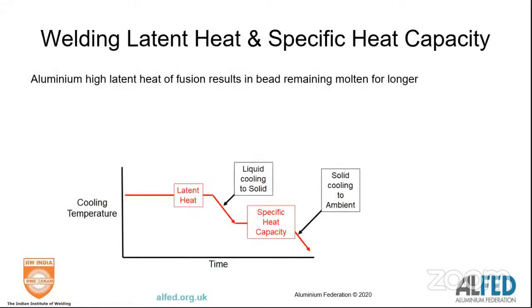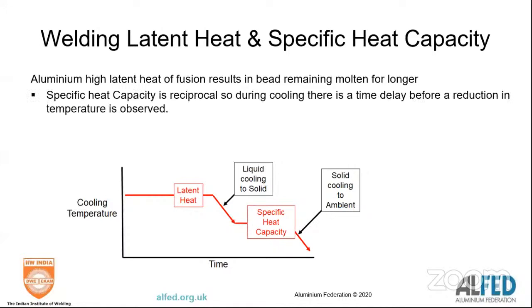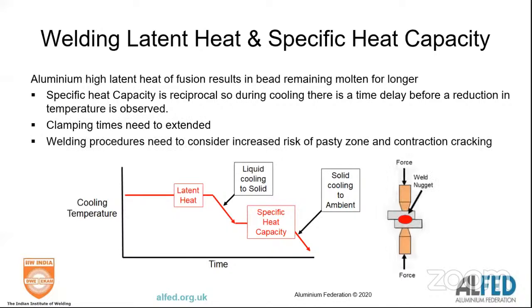And again, the problem with aluminium is its high specific heat. So when you're cooling aluminium, you've got to hold it for longer to allow it to cool. So your clamping times need to be extended. And when you're welding some of them, be aware of the contraction in the heat affected zone.